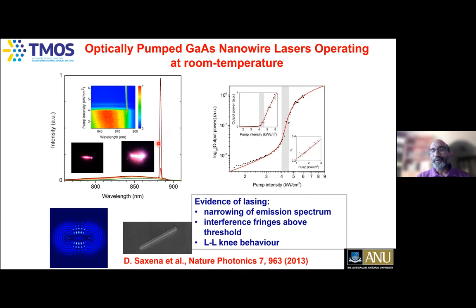And you can see the light output versus pump intensity. Below threshold, you see spontaneous emission of light, behaving like an LED. Then you see amplified spontaneous emission, ultimately lasing. Typically we plot this on a log-log plot, to see whether you've got the S-type curve or not, to confirm that true lasing is taking place.